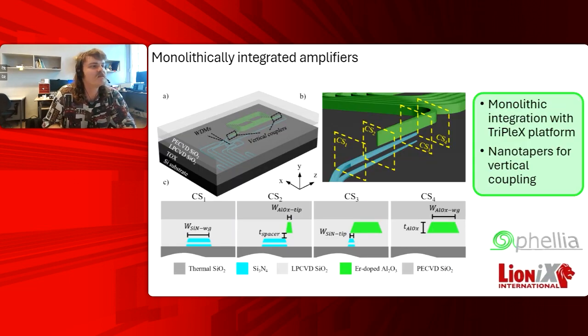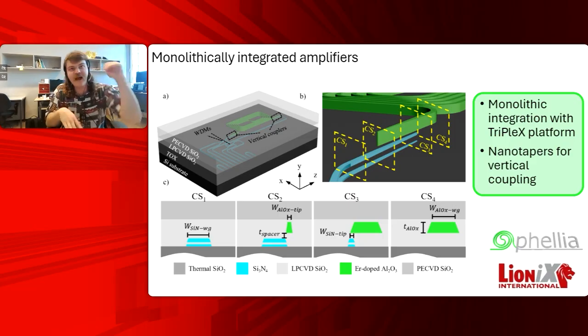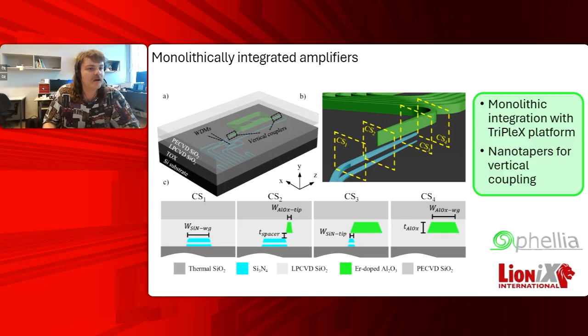Another flavor that I mentioned was this monolithically integrated amplifier, where benefiting from this reactive sputter deposition platform, you can simply, after doing a CMP step and flattening out, done by LioniX, just in our same clean room, we can then deposit on top of the LPCVD cladding our doped aluminum oxide waveguides. Do the same patterning, do some alignment with E-beam technology, and we can adiabatically transfer from the bottom layer to our top layer amplifiers with inline waveguide propagation, and then back down to the nitride to do some advanced devices like WDMs on chip, or really low loss coupling at the edge of the chip itself.